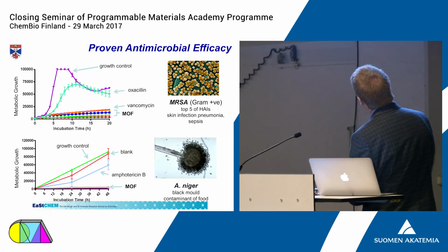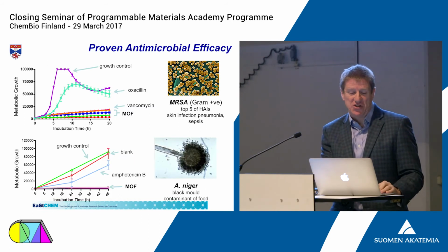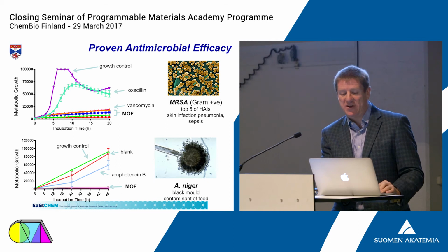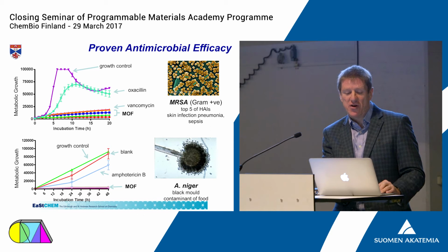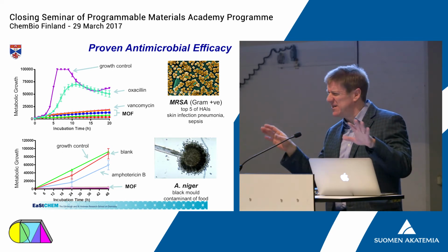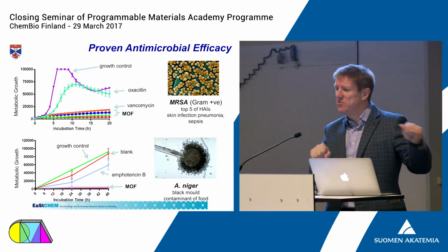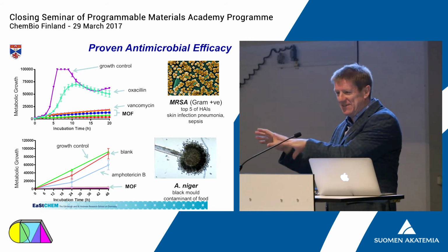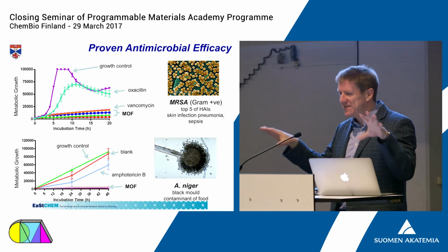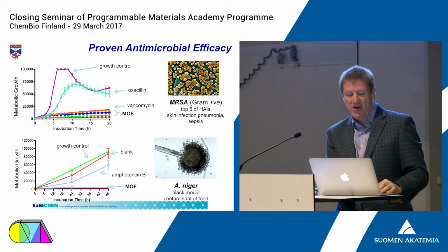Well, these slides are quite complicated, but essentially what they show is metabolic growth of MRSA in this case, right, which is obviously a well-known resistant material. And we could show that the actual metal organic framework itself is as good as the antibiotic. Measuring the different doses is a little bit tricky, because we've got a solid which we're coating on a surface versus a soluble antibiotic. So getting the measurement to be exactly the same is actually quite tricky.